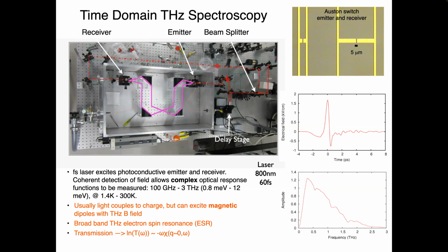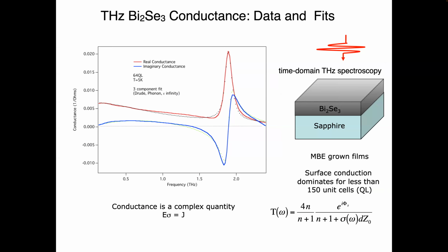Okay, so here's an example of data with time domain terahertz spectroscopy, some early data that we took on topological insulators. And so it's a good way to kind of start thinking about the kind of experiments that one does with time domain terahertz. This was bismuth selenide, okay, topological insulator. It's a thin film of bismuth selenide grown on top of sapphire, grown with molecular beam epitaxy. We measure, again, the real and imaginary parts from the transmission through the sample.